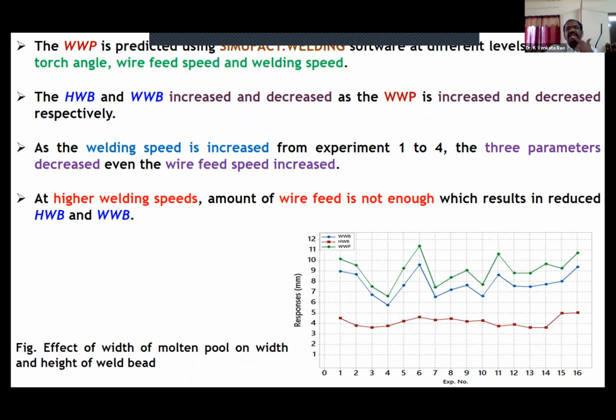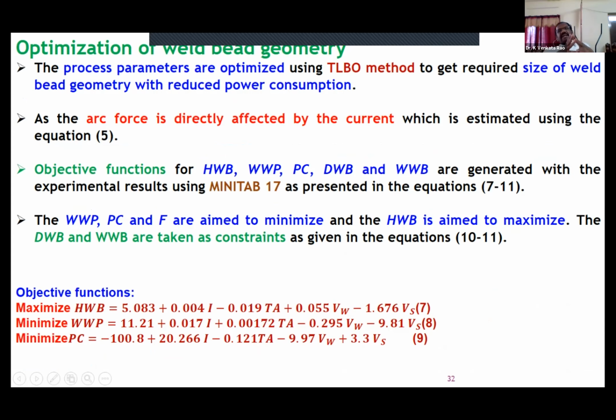So that we are seeing now. In this slide you see the correlation among the width of the weld bead, height of the weld bead, and width of the weld pool. The green line is the width of the weld pool. When it is increased, the width of the bead is increased. We can see the correlation among the three output characteristics. Now, using the TLBO technique, we want to maximize the height of the weld bead and minimize the width of the weld pool. If you are able to minimize the width of the weld pool, we can minimize the depth of the weld bead, and we want to minimize the power consumption.